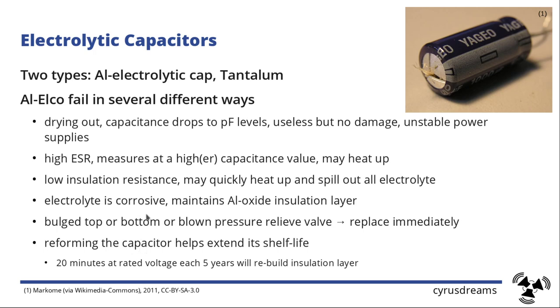Not using electronics, not having power on the capacitors, they will degrade, and the insulation layer from the aluminium oxide will reduce. So it is good practice to power up your gear at least every 5 years for at least 20 minutes. It normally says at rated voltage, because you need the proper voltage applied to the capacitor. But if it's built into your device, you just put it on the power supply, and that should rebuild the insulation layer for that capacitor and prolong its useful life.